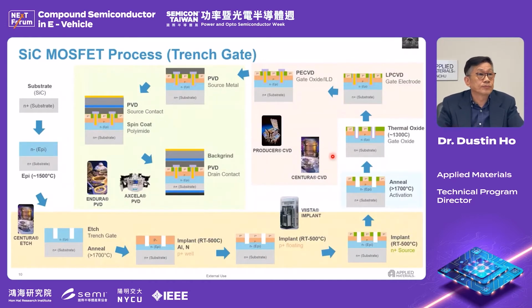And now we look at the MOSFET process. This is a typical process for the trench gate. You have the silicon carbide substrate, and then you need to do the epitaxy, then you need to do the etch. I'm sorry, the cartoon is not really good, because to reduce the high voltage breakdown, the bottom of the etch is more round, it's not a rectangle. Okay. Then you have the trench gate, and then you need the implant. Because it's an N-type substrate, you need a P doping and a P plus doping. Because silicon carbide is a very hard material, you need a high temperature for the doping, and then you anneal at a high temperature, more than 1700 C.